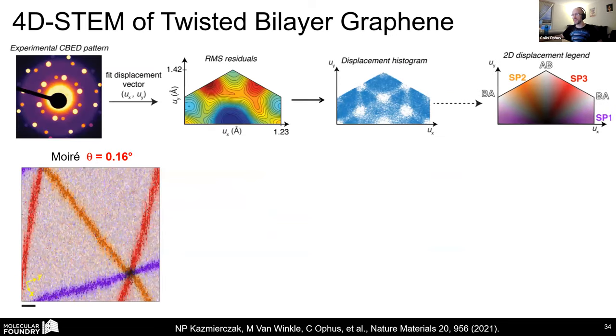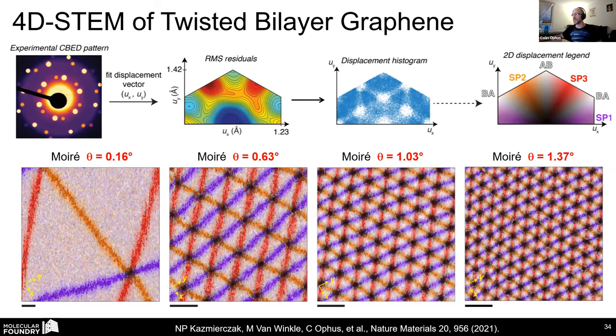And the result of this is a displacement map as a function of the moiré twist angle here. And so you can immediately see, we've labeled here in white the AB stacking and in black the AA stacking, the response of this material as it locally deforms to maximize AB stacking and minimize AA stacking.